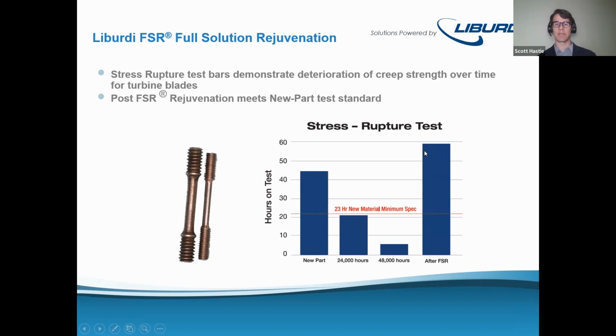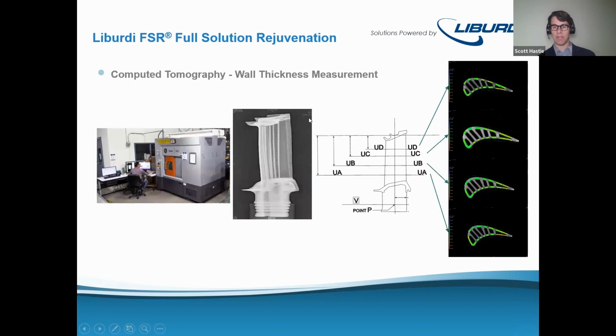This is just data, so I can't change it, but it turned out that our stress rupture test ran longer than the new part material, but really all that matters is that it's above the new material minimum spec after the full solution rejuvenation. So I've got a couple slides here to wrap up. Once you eliminate creep life as a life-limiting mechanism for a turbine blade, because you're able to do rejuvenation and return them to service, you're just basically shifting what the life-limiting feature of that component is.